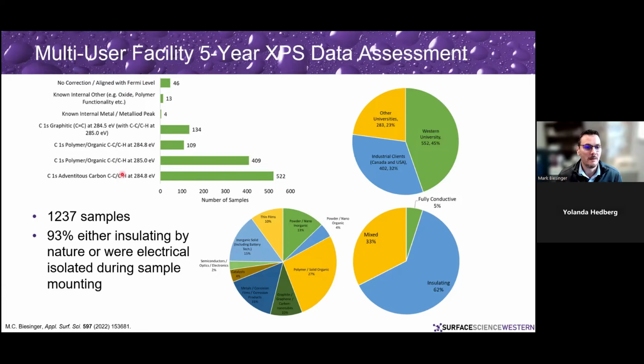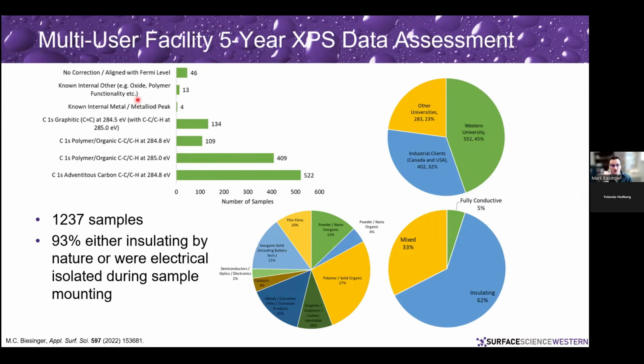Sometimes we've done charge correction for adventitious carbon. Over 500 of those samples we used adventitious carbon. A lot of those samples were polymeric or organic in nature. And so while we were charge correcting to a carbon hydrogen alkyl peak, it's not adventitious carbon that we were charge correcting to. So it's a difference there. It's not the same thing. Same with polymers. We had a lot of polymers and stuff like that. We had a lot of samples that were graphitic in nature, and so again we weren't charge correcting to aliphatic carbon. We were charging to graphitic carbon, which is a different charge referencing number. And sometimes we were able to use other internal peaks as well.